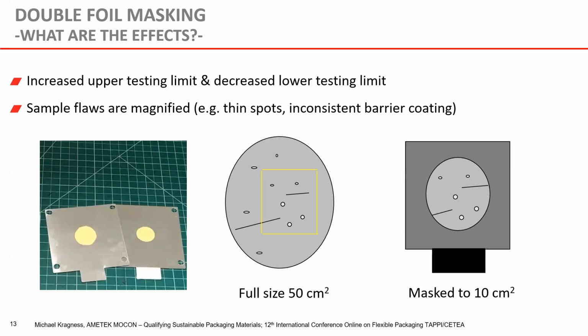Now, one thing to keep in mind is when you're double foil masking, which is essentially sandwiching your material in between 2 foil masks, and you have some well-defined test area, you have to be careful what area you actually mask, because this area should really be as consistent as possible and not have thin spots or other flaws within the area, because that's going to become magnified. That's going to heavily influence your results. So you'll want to find a piece of material that is very consistent, has a good robust coating on it, to where the coating has a consistent uniform thickness. There are no flaws in the material, like a crack in the coating or maybe a pinhole. And that will give you your best chance at getting good repeatable data.